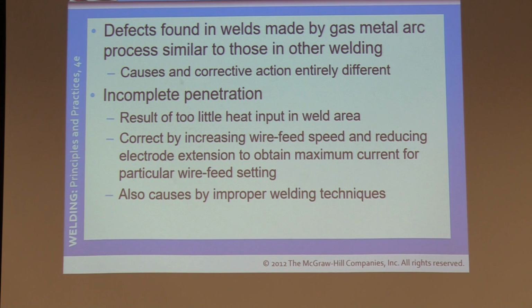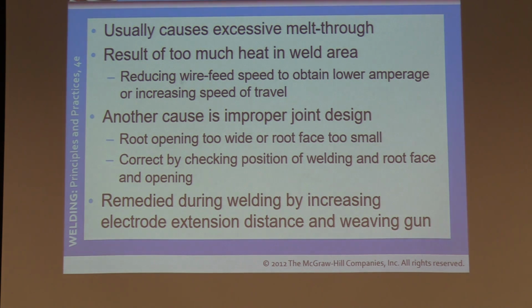All right. Incomplete penetration is the result of too little heat input into the weld area. Correct by increasing wire feed speed and reducing electrode extension. Excessive penetration usually causes excessive melt through, really heavy icicles on the back. Back your voltage off, your wire speed off, maybe increase your travel speed, things like that. Okay. Too much heat into the weld area also can cause distortion as well.